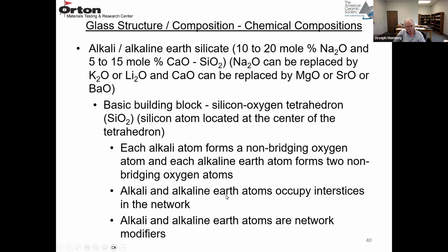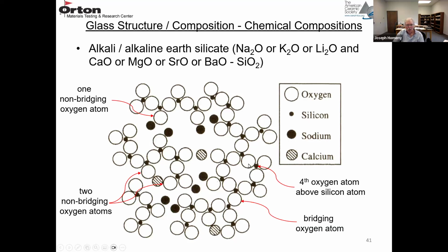The alkali and the alkaline earth atoms occupy these voids or interstitials in the network. Both alkali and alkaline earth atoms are network modifiers. They are not glass formers or glass intermediates. So this is what this structure will look like. The open circle is oxygen, the small black circle is silicon. So here's your tetrahedron. We assume there's an oxygen above the silicon atom. The large black circle is sodium, and then the crosshatch circle is calcium.